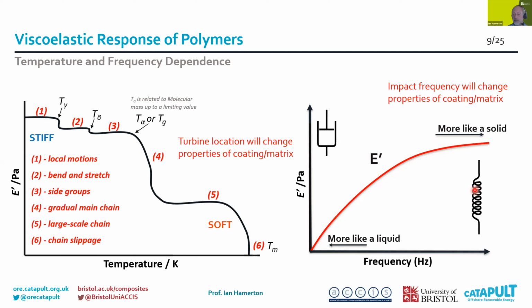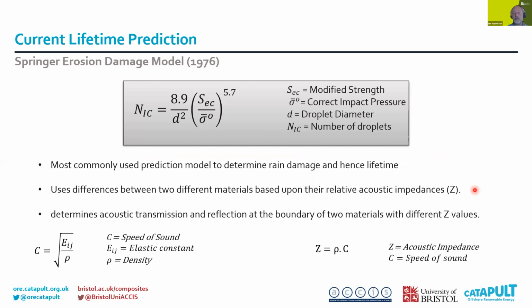So again, the impact frequency is going to change the properties that we observe. So we have to take those into account. And we're working still with relatively old traditional models. So the Springer erosion damage model, which was conceived in the mid-1970s, is still the most commonly used prediction model to determine rain damage and consequently lifetime.